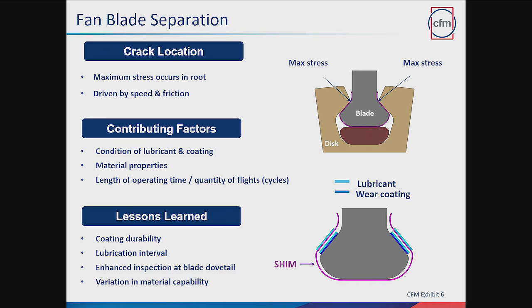So contributing factors, like I said, the coating condition. If that coating begins to wear, it can change the loading pattern on the blade. And also if the lubricant is either not there or a lot of it's gone away and it's no longer doing its job, that can also increase friction. So lessons learned going forward, it's really all about making sure that the contributors to friction factor are addressed, contributors to the material properties. The blades go through overhaul and repair. There's new make variation. All of those pieces of variation can contribute to some blade cracking in the fleet.